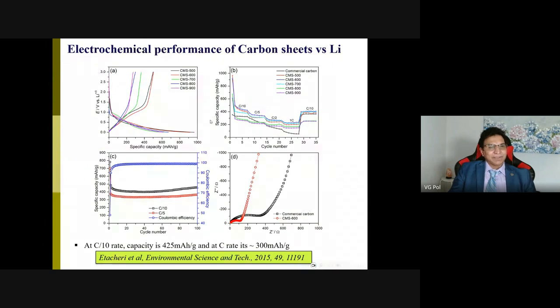And now these batteries are working very happily, delivering very high capacity, as can be seen from the top left diagram. Our top right diagram also says that even when you try to charge and discharge the battery within 1 hour, 1C rate means 1 hour of charging, 1 hour of discharging, you still get very reasonable specific capacity out of the battery. And these batteries can charge and discharge for hundreds of times.